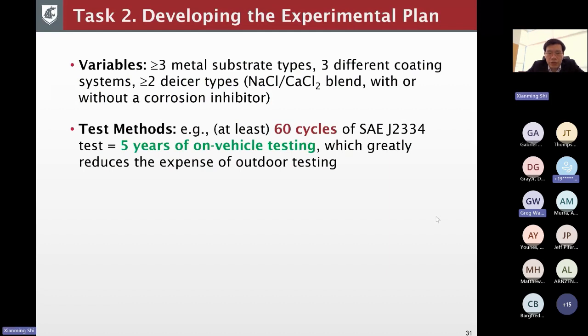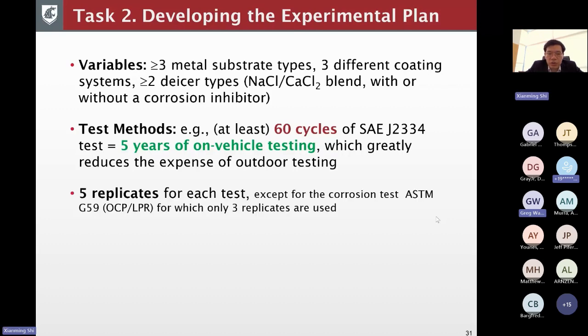The fortunate thing is that there is a well-established lab testing protocol known as the salt spray test protocol under SAE J2334. This salt spray test protocol incorporates wet-dry cycles as well as exposure to salt, so that previous research had shown that 60 cycles of this accelerated test is equivalent of about 5 years of on-vehicle testing. With this accelerated lab test, one can greatly reduce the expense of outdoor testing. And maybe that is partially why we couldn't find any field testing results, because the SAE test protocol is pretty reliable. And for each test, we typically use 5 replicates, except in some cases we use 3.